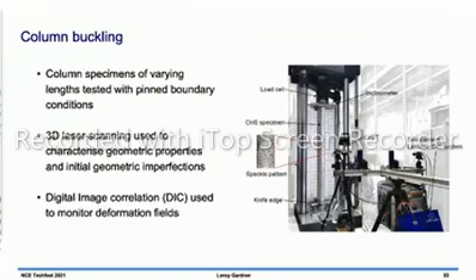So that was looking at cross-sections and short columns. We also looked at longer columns. We tested them with pin-ended conditions, so we're looking at their buckling behavior. And this is an example of where we used digital image correlation to track the deformations of the specimens, and you can see how it failed. So this is a combination of overall buckling and local buckling of the columns. And again, if you compare to current design guidance, provided you use the properties of the as-built material with the effect of the geometric undulations, broadly speaking, current design curves quite well predict the behavior of these sections. So this was comforting.